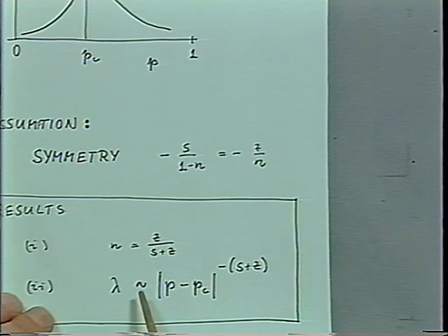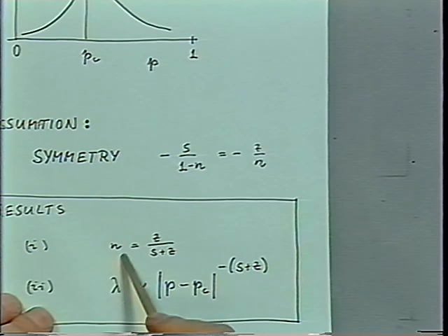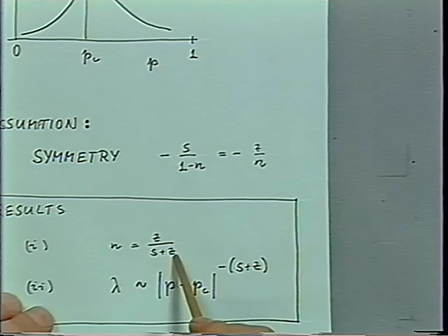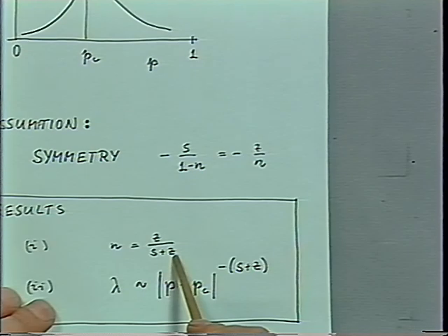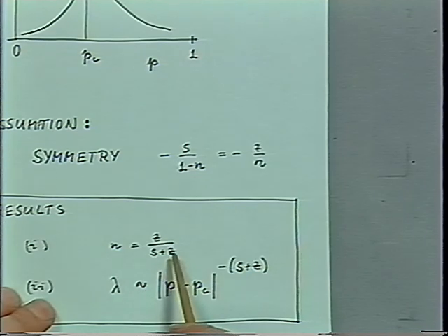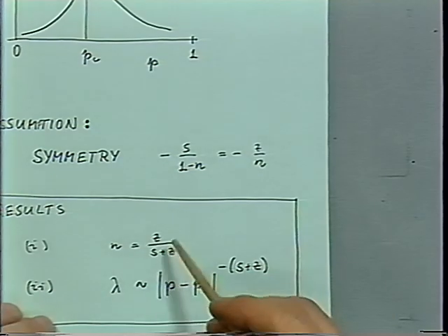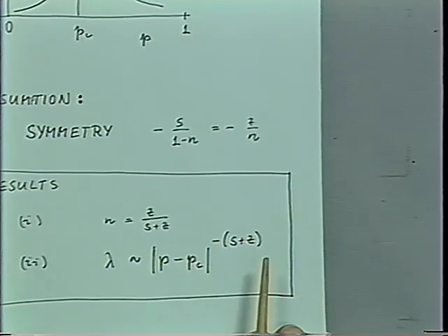That's a very interesting result. You can already say that if n is a material parameter, if that changes from critical gel to critical gel, and we know it does, then z and s cannot be universal exponents. And that has an impact, a very deep impact on polymer physics. So just by doing a few harmless experiments, we're causing lots of trouble here to basic physical arguments. Okay, so this is a first interesting result.